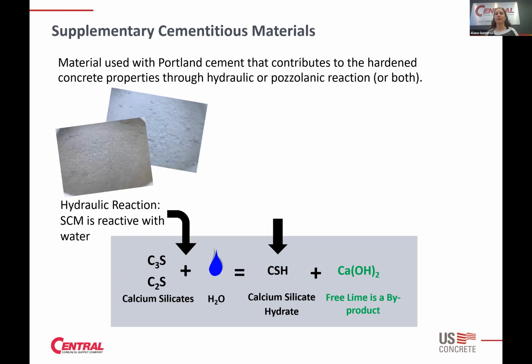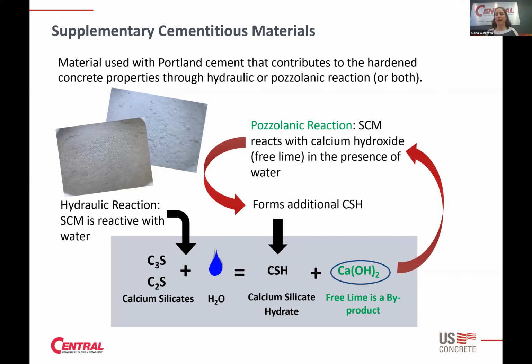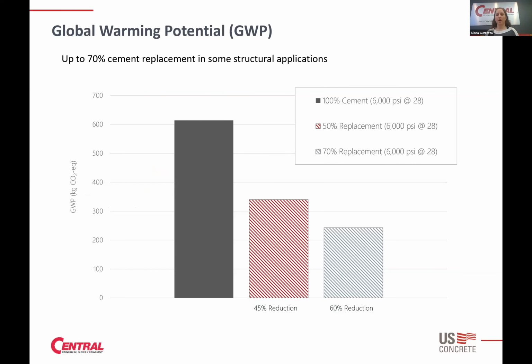And the benefit of supplementary cementitious materials is that some will have a little bit of reactivity with water on their own, but the majority of what they're doing is they're reacting with that calcium hydroxide, that weaker product. They're reacting with that and water to form more of that CSH, or that strong part of the paste. And so what that's doing is going to increase the strength of your concrete and also make it more dense as well.